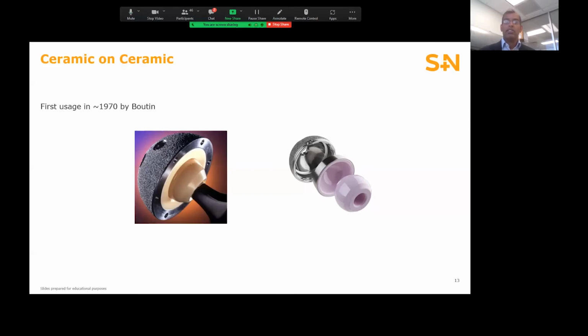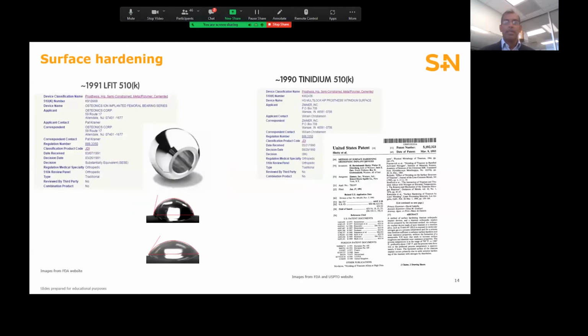As I alluded to, modern ceramics, in particular the zirconia toughened alumina, are quite fracture resistant. Despite that being the case, there are rare instances where you do get a brittle fracture. And in those cases, small hard particulate are liberated in the joint space, and it makes for what can be a challenging revision procedure. Due to their surface characteristics, ceramic heads are still used in hip replacement.